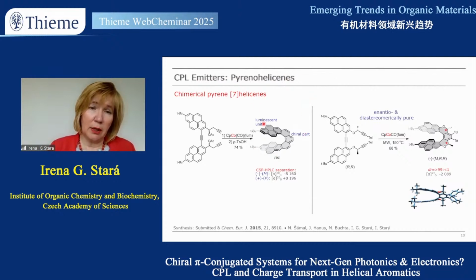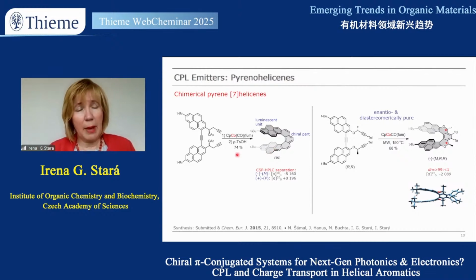The luminescent part is just this pyrene, which is a highly luminescent unit, and the helicene part brings chirality. So we speculated that when we make such a model and extend the pyrene unit, extend the aromatic system, it would lead to enhanced luminescent properties. First we prepared such a helicene, shown here as a racemate, and we used chiral HPLC to prepare enantiomers. We also designed and prepared another compound incorporating oxygen atoms, and this one was prepared by asymmetric synthesis.